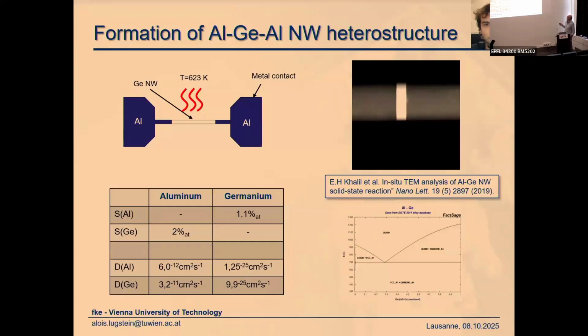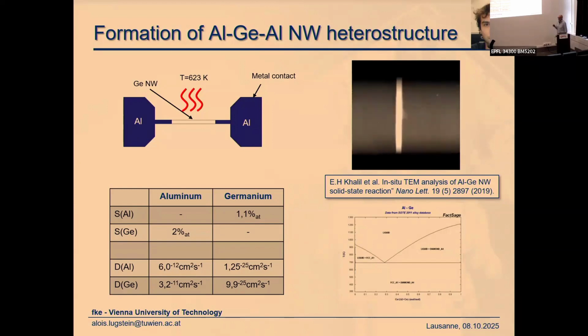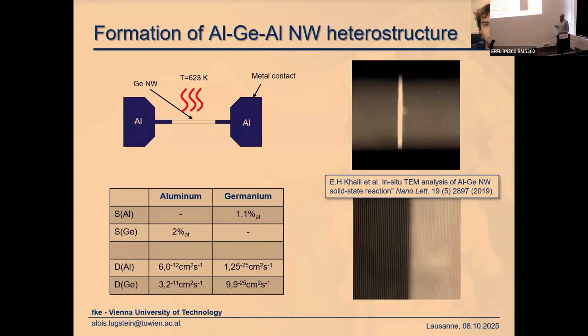The germanium is diffusing into the enlarged pads and is replaced by aluminum. For this particular system, as you see in the phase diagram, there's no stable germanide. So this is really a complete exchange of germanium by aluminum. And this is the image that I've shown in the first slide.